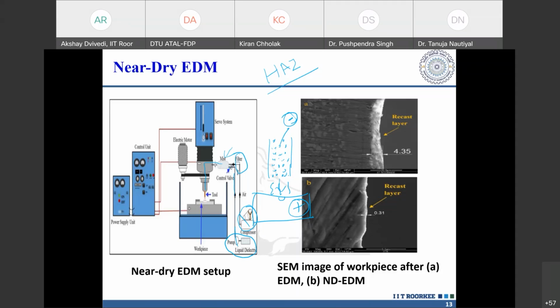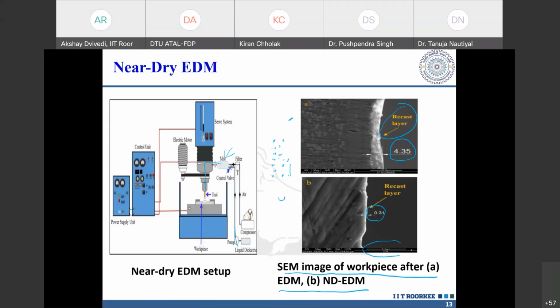Looking at the quality that you get from this particular case, I have a comparison where there is the same image of a workpiece after conventional EDM and near dry EDM. Now in this comparison, you can see that there is a recast layer, which is mentioned with a number 4.35. And here in this particular case, I have a number of 0.31. And by the way, you have somewhat the same scale, which is 5 micrometer.